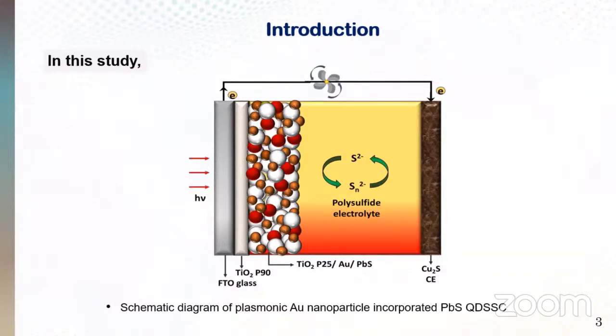PbS quantum dots generate electron-hole pairs by light absorption. These electrons get injected to the conduction band of TiO2 and flow to the external circuit, finally reaching the copper sulfide counter electrode. Polysulfide redox couple regenerates PbS quantum dots and transports holes to the counter electrode. In this study, colloidal gold plasmonic nanoparticles were added to the TiO2 photoanode in order to enhance the performance of QDSSCs by using their LSPR effect.